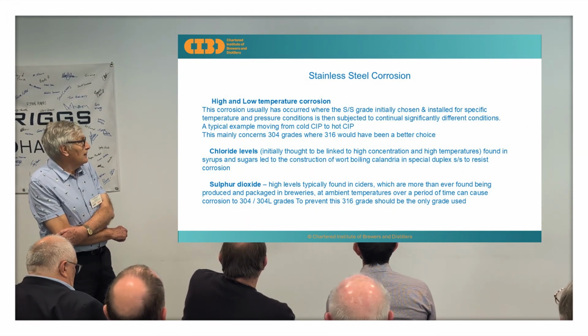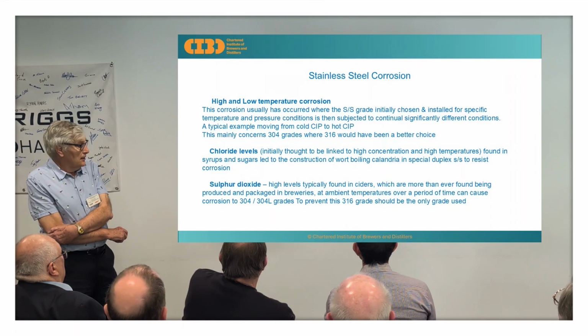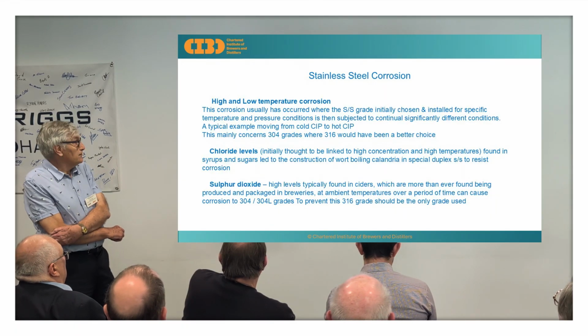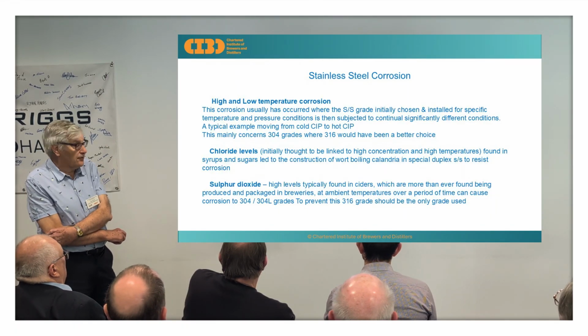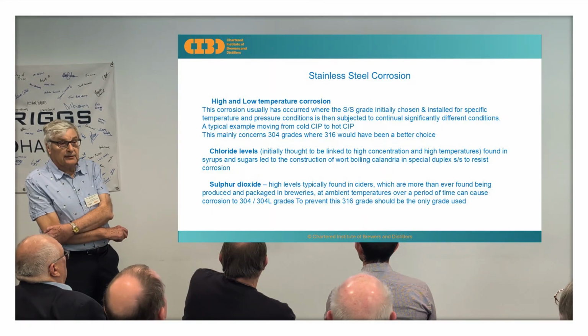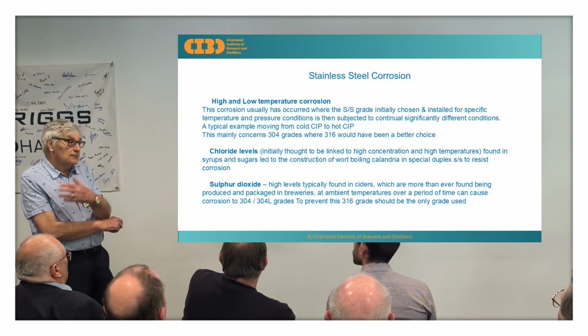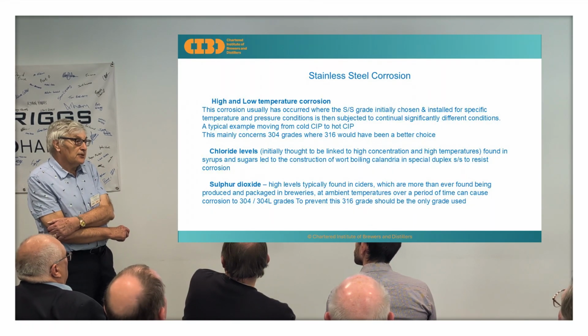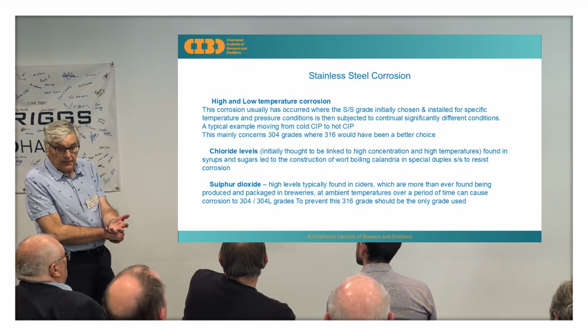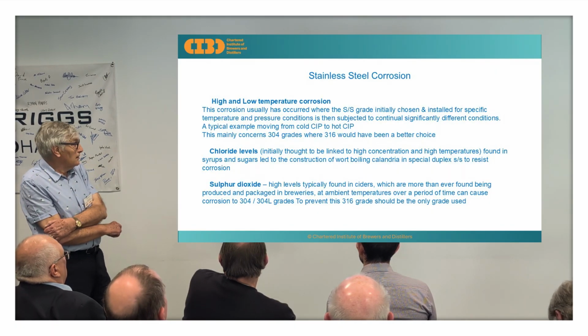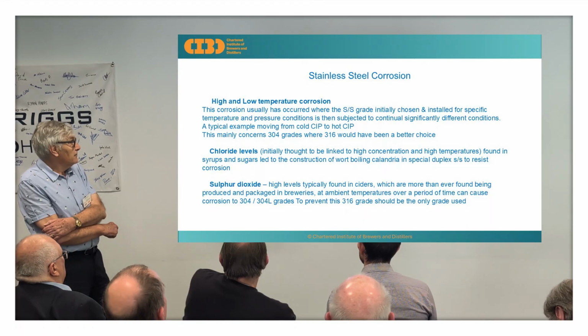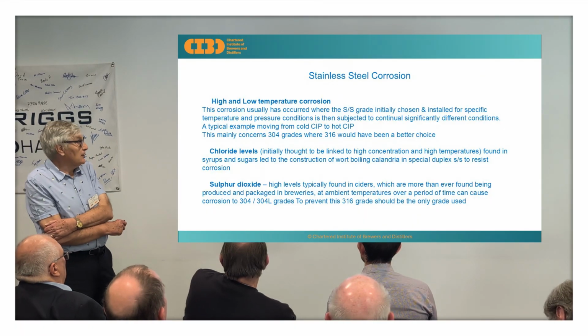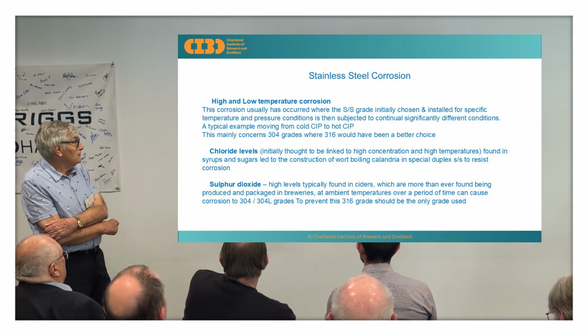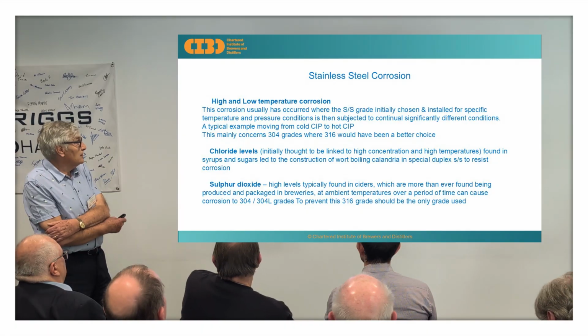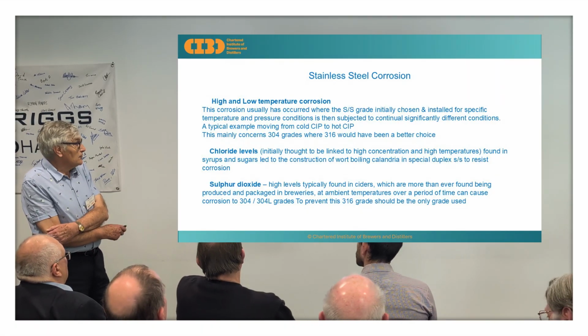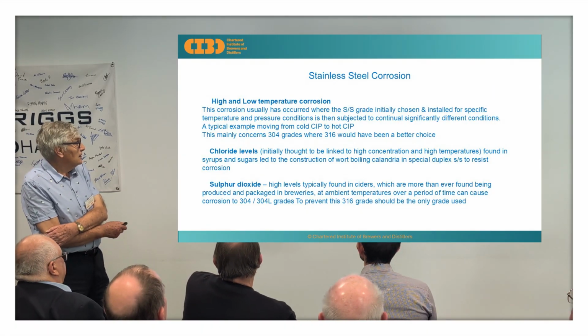I've seen this where we've had cold CIP centres put in using grade 304, and then the brewer thinking, well, I want it to be a hot CIP because I can reduce the time of my CIP regimes, has gone to hot CIP and then ended up with corrosion. 316 would have been a better choice.